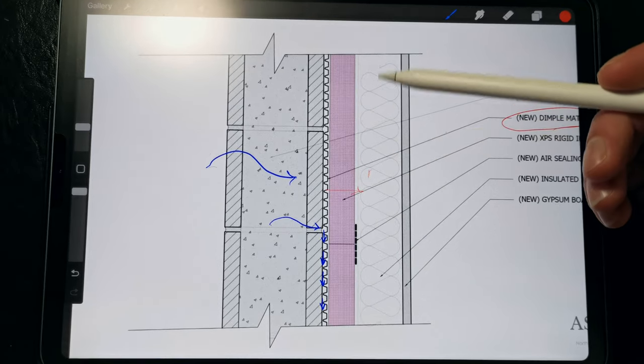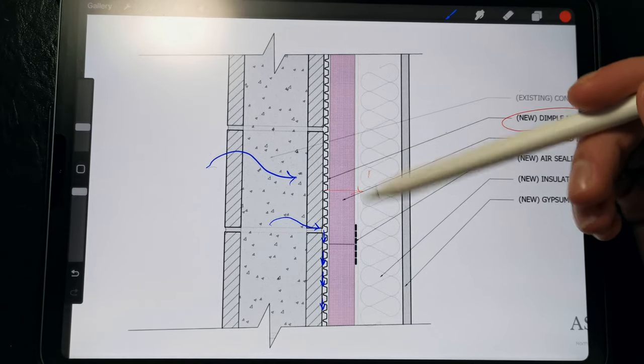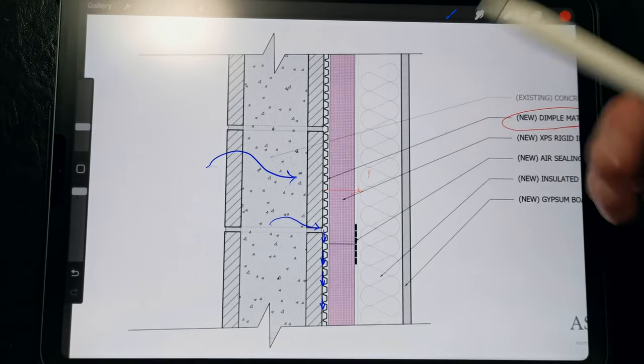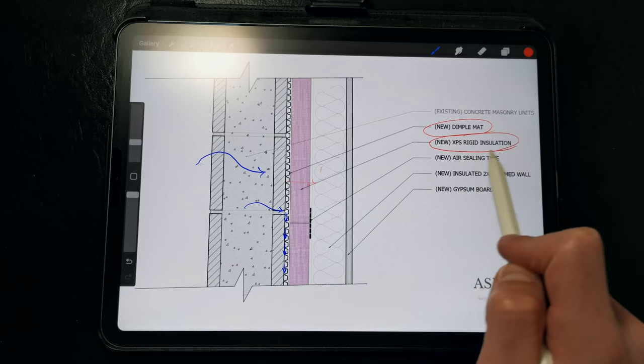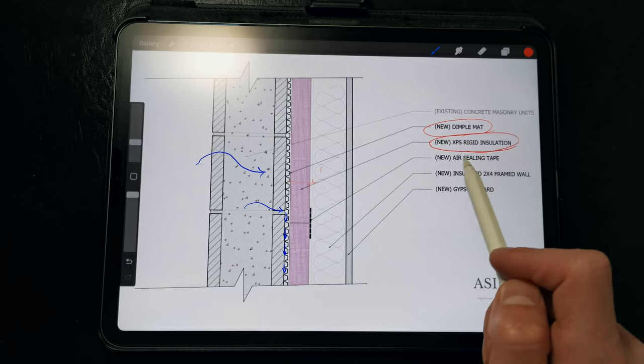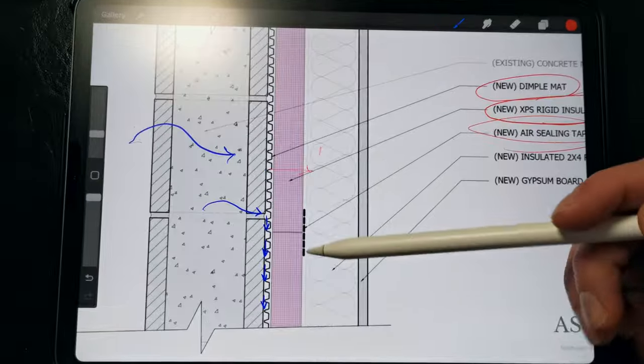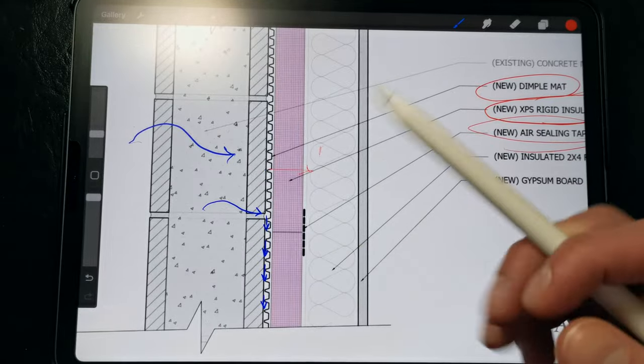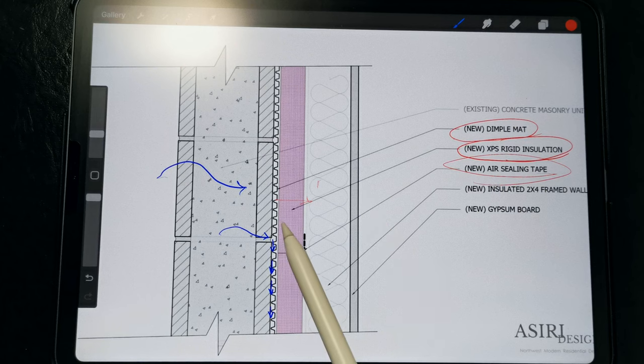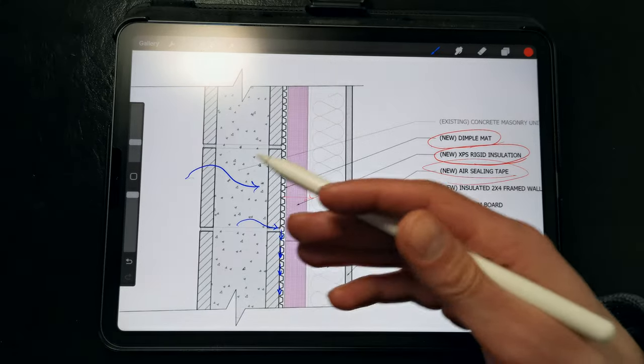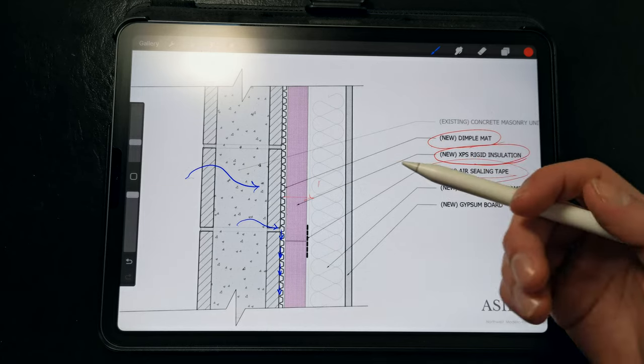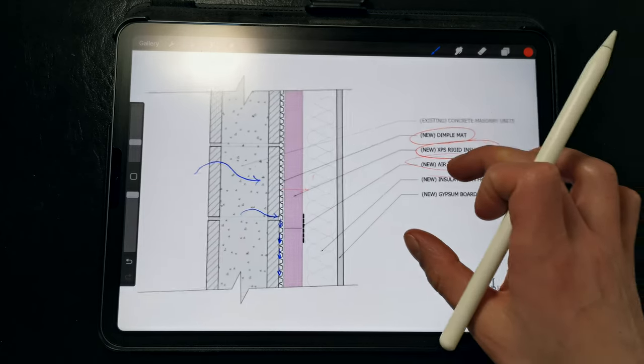It also allows us to insulate the interior space with whatever insulation strategy that we want. Here in this detail, we have taped extruded polystyrene, which is specified here to prevent condensation on the backside of the dimple mat. If you're located in a warm climate, you don't necessarily need this, but this XPS provides a nice thermal break and it prevents air leakage and vapor diffusion that could deposit moisture on the backside of the dimple mat in colder and more temperate climates.